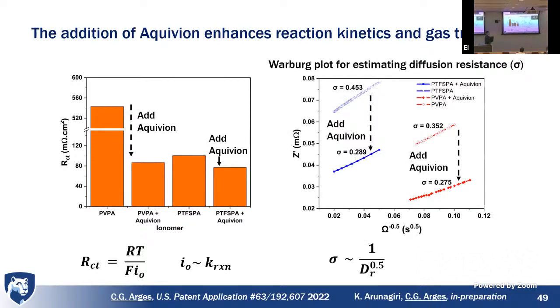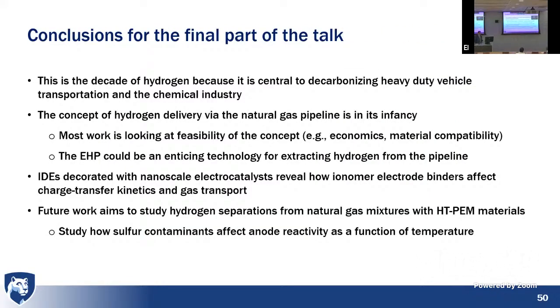And then if we look at the gas diffusion, in the Nyquist plot, the low frequency regime, we can calculate the diffusion resistance, which is 1 over the square root of the diffusion coefficient. We see the Aquivion is reducing the diffusion resistance sigma here, and that's because we're promoting diffusivity in the electrode layer. So this binder also affects not just kinetics and conductivity, but gas transport. So this is the conclusion of my talk. This is the decade of hydrogen.